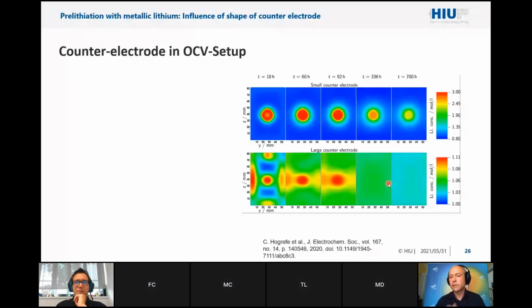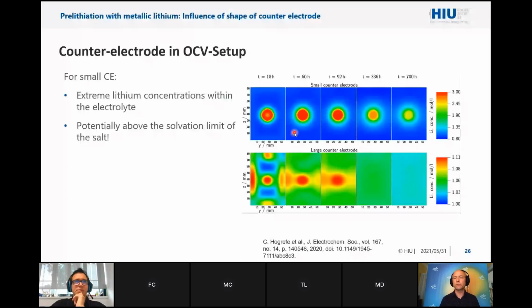And this is a nice picture of how different the lithium concentration in the electrolyte is for the small counter-electrode compared to the large counter-electrode. And if you now think what is going to happen in a lithium plating event where you have a counter-electrode, a real cathode, and you keep it in an open circuit situation, then you know that also something is going to happen really non-locally on the cathode. And another interesting question is, how does this bigger anode, which is very often used compared to the cathode, how is this asymmetry influencing the cathode due to these very non-local phenomena?